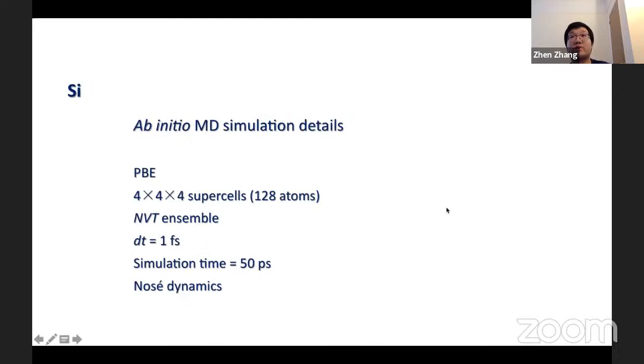Here are the ab initio MD simulation details. PBE was chosen for the exchange correlation functional. 4x4x4 supercells equivalent to 128 atoms were simulated in the NVT ensemble. Each MD ran for 50 picosecond with a time step of 1 femtosecond. Temperatures were controlled by Nosé dynamics.